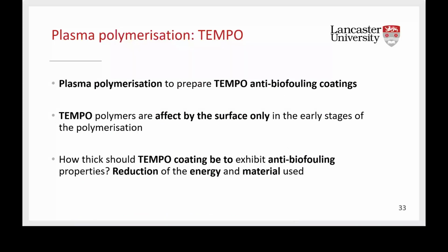So TEMPO plasma polymerization can be used to coat TEMPO, a well-known anti-biofouling agent, on surfaces. I noticed that TEMPO polymers are affected by the surface only in the early stages of plasma polymerization. And when they are 30 nanometers thick, the growth becomes surface independent. The next step of the research would be to test this 30 nanometer thick coating for anti-biofouling activity, because if they actually exhibit any anti-biofouling activity, we can massively reduce the amount of energy and material used with respect to the micrometer thick coatings reported in literature.